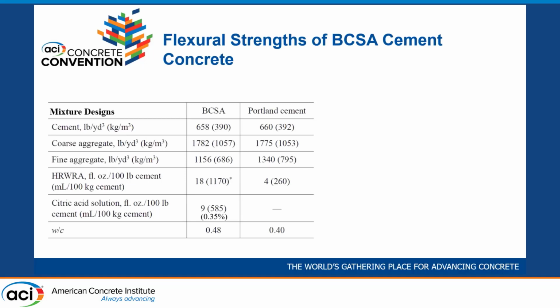This is what our mixture designs look like. So BCSA is on the left here and Portland cement is on the right. We tried to match the quantity of cement and coarse aggregate because we figured these were going to have some impact on the flexural performance. But you see we have a different water cement ratio, slightly different fine aggregate content, and this is just because the specific gravity of these cements is a little bit different. But there's also more high range in the BCSA beams.